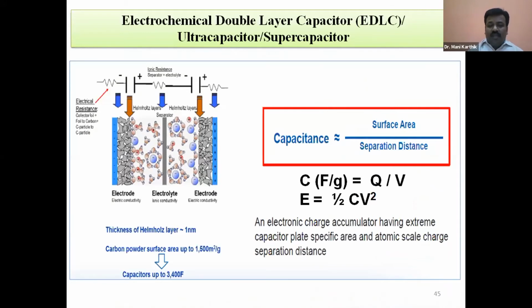So when the electrolyte is put in, there is a formation of the Helmholtz layer. That's why it is called the electrical double layer. You can see the formula: capacitance in farads per gram is Q by V. The energy density E equals half C V squared. Even though the capacitance is very important, the voltage is very important because of the V squared. If you increase to a higher voltage, then your energy density is very high. That's the reason we are using the organic electrolyte as compared to the aqueous electrolyte.